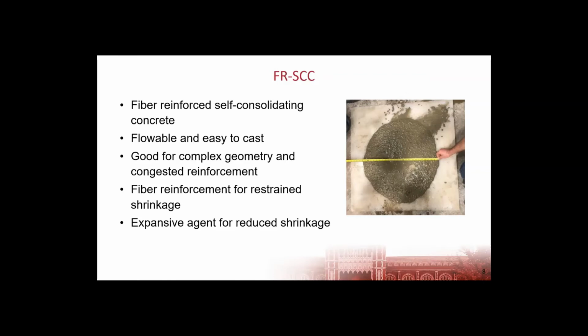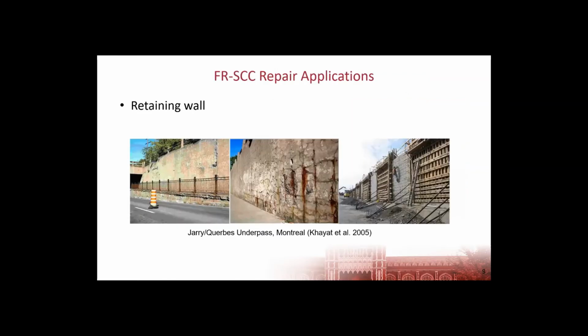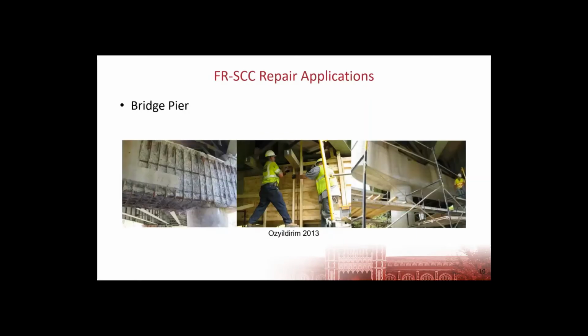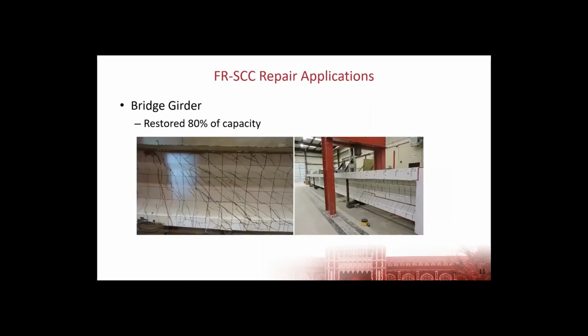This material has been used in some different applications, such as some retaining walls in Montreal, some bridge piers in the US, and then some of the work that's been done here at OU related to bridge girders was to take a full-size AASHTO Type 2 girder that had been taken out of a bridge and been tested to complete failure in flexure and shear at each end. And then the damaged sections were actually jackhammered out, which you can see here in the picture on the right in the red outlined region.